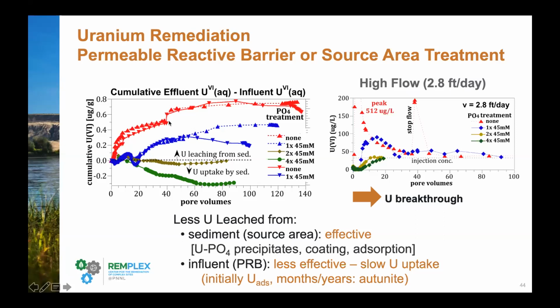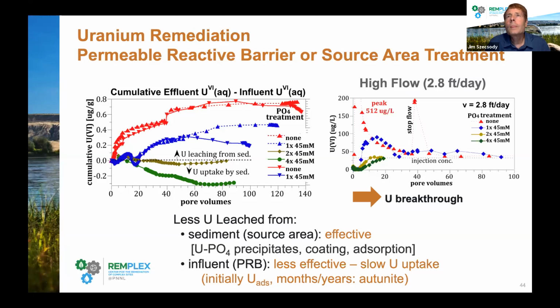Excellent, thank you. And you talked about this a little bit, but Chris Halter asked, could this phosphate treatment be a long-term solution for uranium contamination at the Hanford and Rifle sites? We do think it will be effective long-term, because we think a little bit of autunite forms initially, but then the apatite, which is the main phosphate phase present, over time, uranium will adsorb to that. And then over even more time, over years, some additional autunite will form because there's a little bit of phosphate solubility, and that adsorbed uranium will react and form autunite. Autunite is a very low solubility phase, which should stay stable in this environment for a very long period of time.